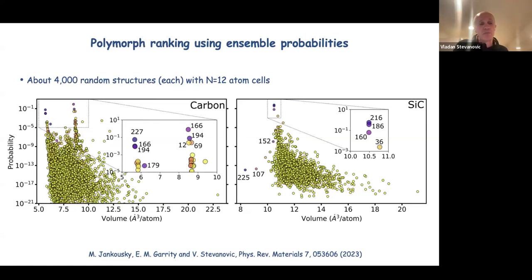So what I'm showing you here is the ensemble probability distribution calculated at room temperature. Again, temperature doesn't really affect the ranking. It will broadly affect how much in probability two points differ from each other, but not their relative position in probability. So room temperature is just something that we assumed. And that probability distribution is shown against the volume of each structure. And here for elemental carbon, to the left, you see in yellow there are many yellow points, which are the very low symmetry, space group number 1 and 2. And those that are colored have space groups that are labeled in this inset. And for elemental carbon, by the way, relaxations here were done with van der Waals corrected functionals.